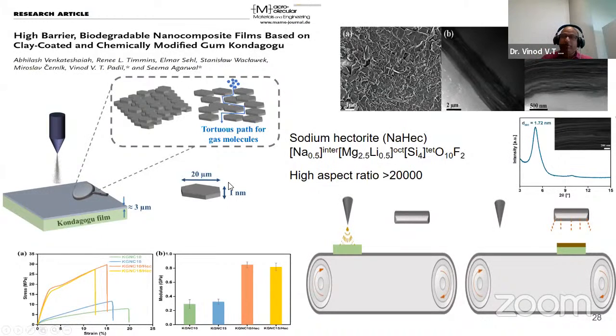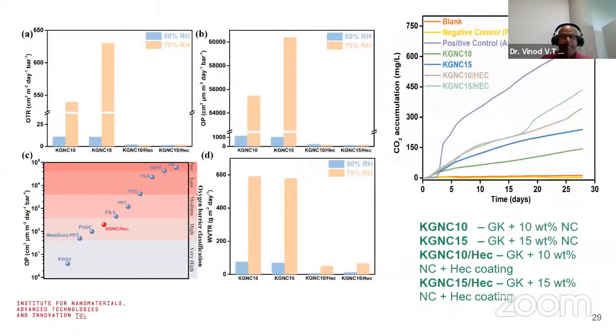So after addition of this sodium hectorite, this film showed exceptionally good properties like barrier and mechanical properties. So this method also gives an environment friendly material. After making the clay modified films, it can easily biodegrade also, like a natural gum material. So the biodegradation we observed is more than 90%.